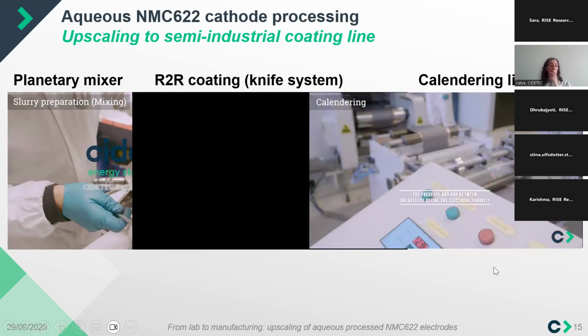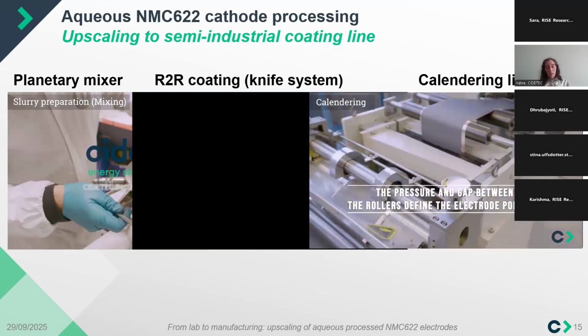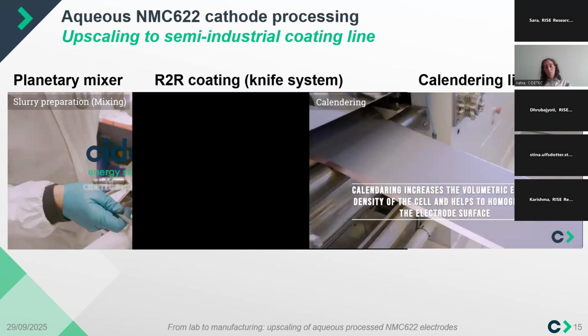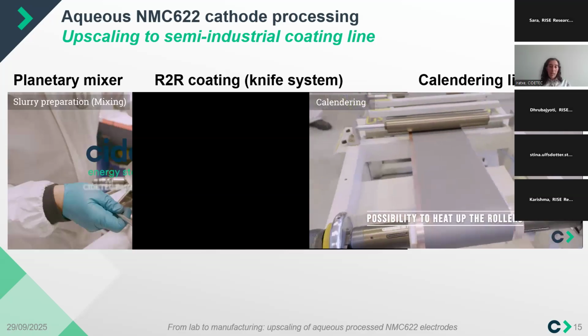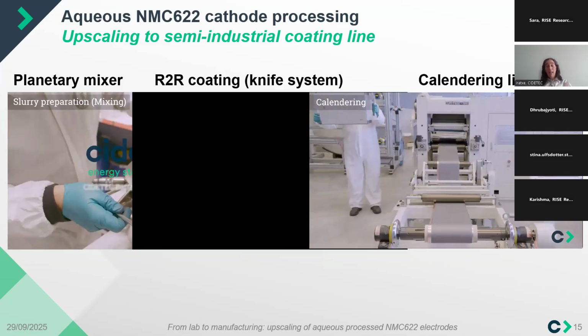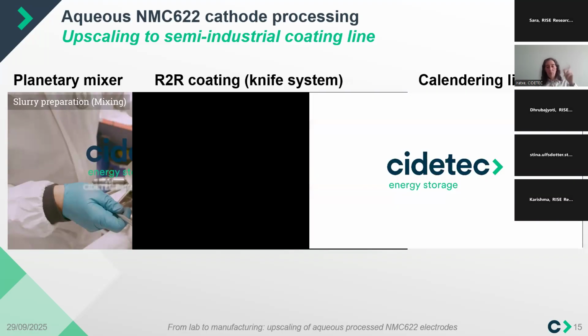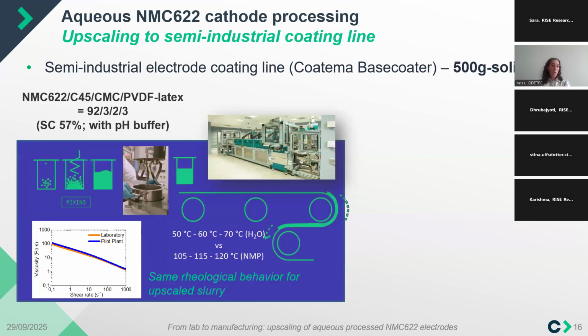This will be the calendering, which is kind of the final step after coating, roll to roll, and drying. You go to this calendering, which uses two rolls that compress the coated layer to densify it to the optimum density for the designed cell performance—either to maximize energy density, compacting as much as possible without losing the required power rate, or to match the design of the cell at the optimum depending on the active material and the formulation.